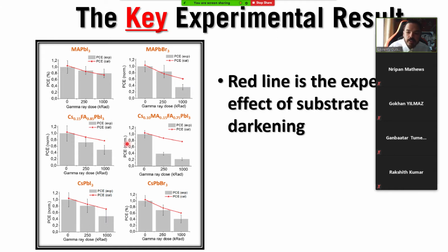When we analyze this diagram, we have power conversion efficiency on the y-axis and the gamma ray dose on the x-axis. When we start at the bottom, we expect cesium lead iodide to be more stable than methylammonium lead iodide, MAPI. But it's not. It degrades much more when irradiated by significant gamma ray doses. And when we look at bromide-based perovskites, they are even less stable when irradiated by this ionizing radiation. That is, of course, a completely unexpected result.